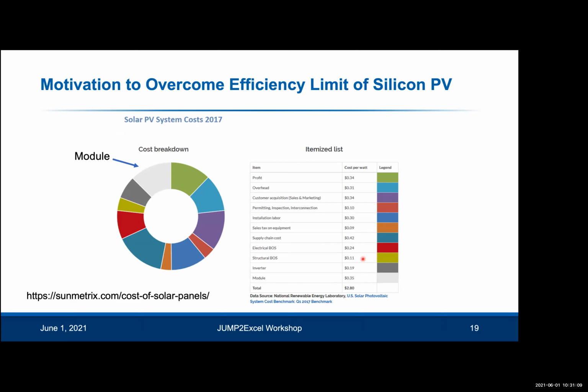So if you improve the efficiency of silicon by 1 or 2%, you're not going to change this overall cost that much. What you could do is make a different structure, and maybe this adds a little bit to the cost. Maybe instead of paying 35 cents, you pay 40 cents. But if you can increase the absolute efficiency by an absolute value of 10%, then you increase the power produced, and therefore you can significantly decrease this cost per watt ratio. So efficiency is an important lever for the levelized cost of energy for photovoltaics.